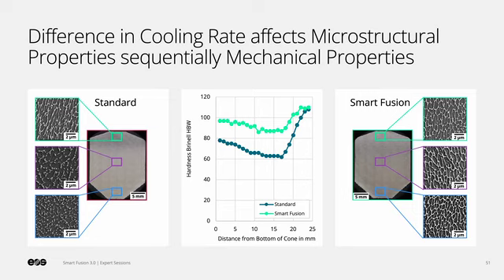On the other hand, applying Smart Fusion results in more homogeneous thermal behavior. Comparing the BSE images on the right side from the sample built with Smart Fusion, the silicon-rich network is getting thicker and more nanoparticles can be detected in the alpha phase. When we are moving from the upper side to the bottom side, where we have a larger exposure area and smaller heat dissipation area, although a small change in morphology can be seen here, the network-like structure still remains through the whole part.